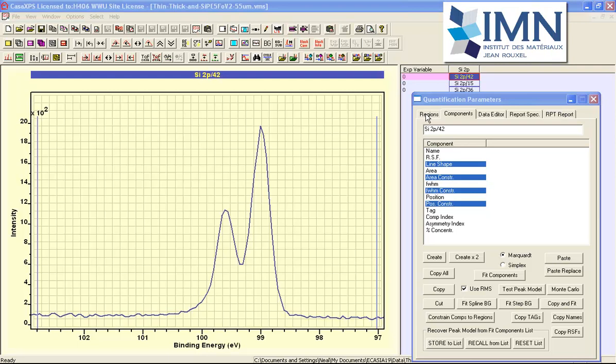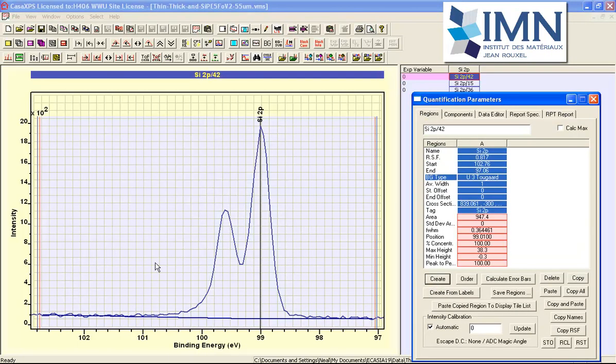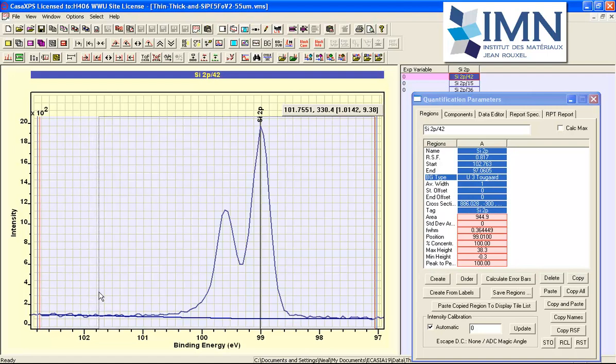The first step in making a peak model is to create a background. I've introduced a U3 Tougaard background, and this allows a smooth variation of signal beneath these photoemission peaks. I'm also adjusting the end limit, and the reason I've done this is because you can see some kind of oscillation here that seems different from the rest of the noise in the background. So this is either the start of some kind of oxygen signal,